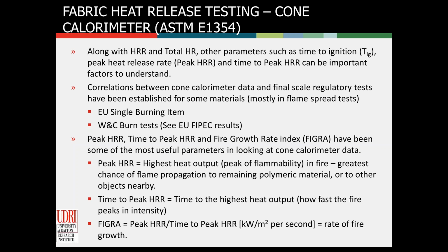It's that fabric in combination with something else that is really what you may want to test on the cone calorimeter to properly see that composite performance and understand peak heat release rate. How fast does it get to peak heat release rate? Is it really, really slow?